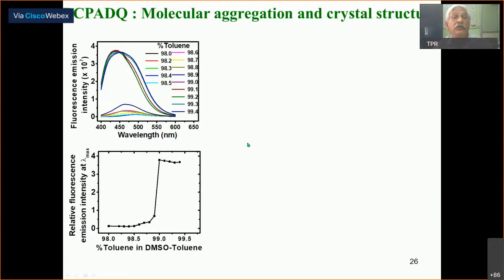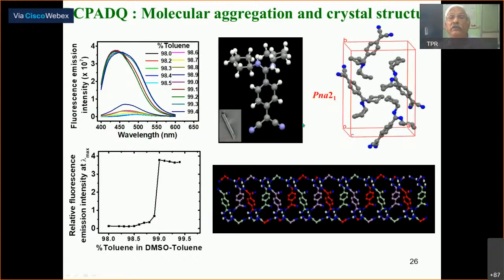And this actually shows the fluorescent spectrum. What happens here is as you increase the toluene percentage in the DMSO or toluene mixture, there is a sudden jump, and this is what people have been describing as aggregation-induced emission. Essentially, there is a sudden formation of aggregates, with a small peak shift and a large intensity increase. And we could do normal crystallography, because if you let it grow properly under normal crystal growth conditions,